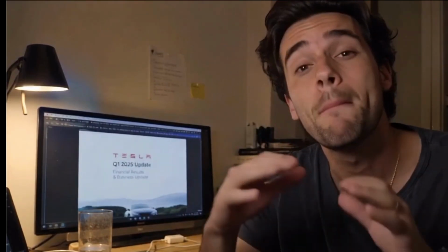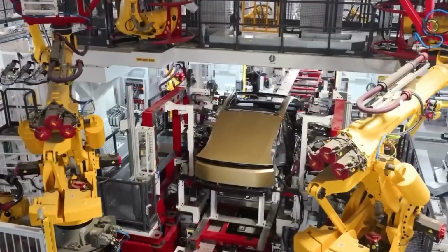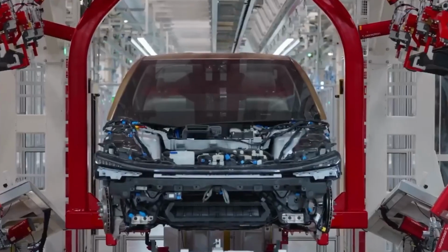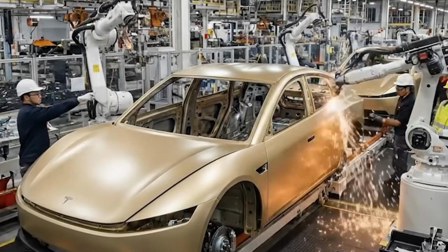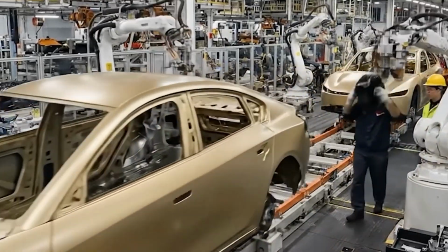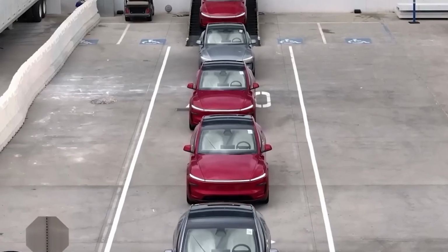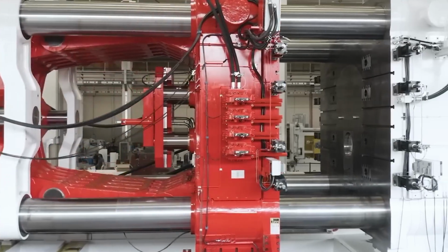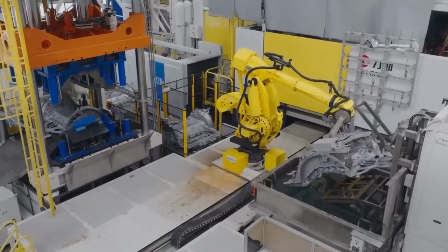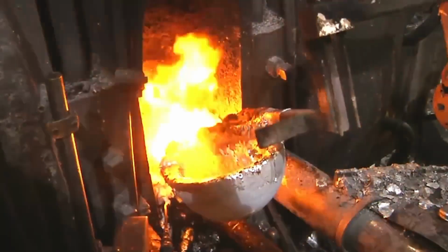The physics barrier that has historically prevented casting at this speed is heat. When molten aluminum at approximately 850 degrees Celsius is injected into a mold under extreme pressure, 2 failure modes are competing simultaneously. If the metal flows too slowly, it solidifies before filling the mold's complex internal channels, producing a defective casting that must be scrapped. If it flows too fast, air becomes entrapped, creating bubbles that compromise structural integrity at the microscopic level. Traditional die casting manages this tension by slowing the process. Longer cycle times reduce both failure modes, but limit output.